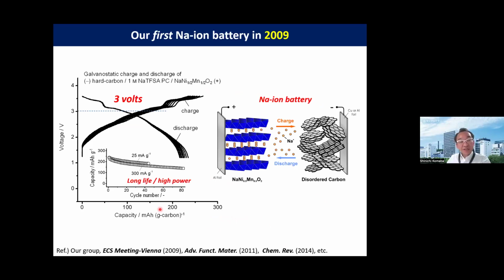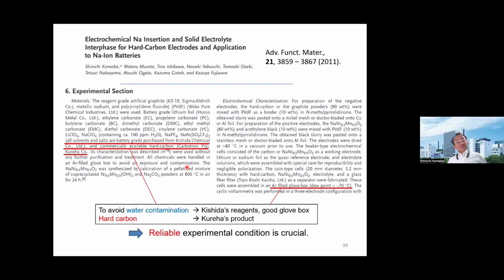In 2009, by combining nickel manganese oxide and hard carbon, that is disordered carbon, and by using the non-aqueous sodium ion electrolyte solution, we demonstrated a 3 volt charge-discharge battery. At that time, 2009, nobody believed in the SEI formation on the negative electrode and also the high reversibility of sodium intercalation into layered sodium oxide.